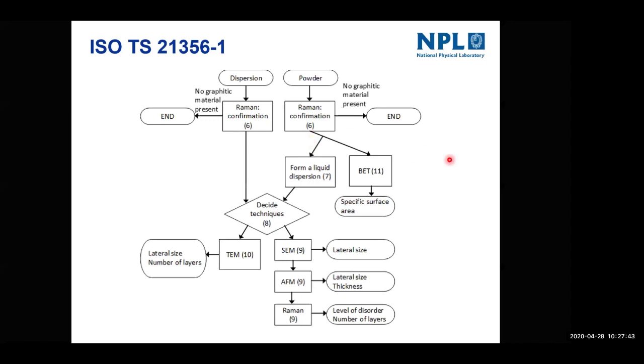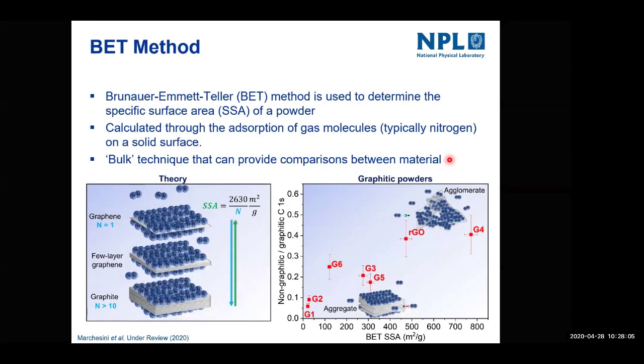So if we look at the current draft of the flowchart, it looks very different to the one in the Good Practice Guide, but essentially it's the same, except that here we have BET as well. So this is a measurement of a powder that's in the standard, and again, it's an important, powerful technique that isn't in the Good Practice Guide, but is in the standard. So what's this technique for those that don't know it? Well, the BET method, or the Brunauer-Emmett-Teller method, is essentially used to determine the specific surface area of a powder.